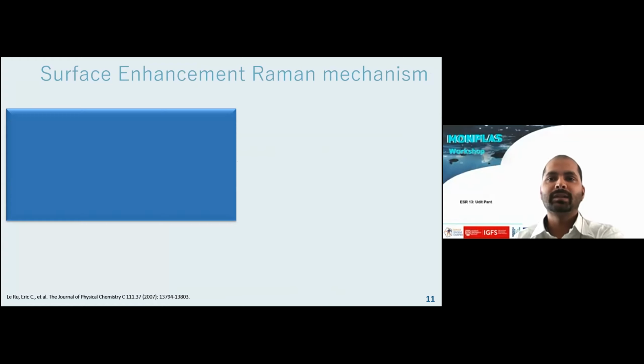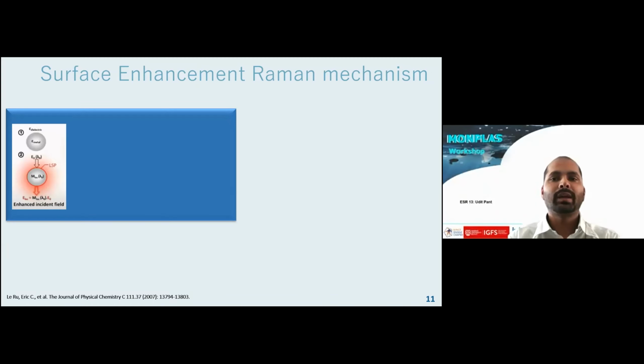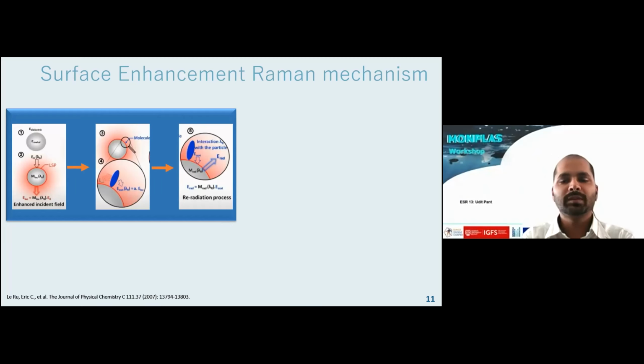There are mainly two mechanisms which are responsible for the large enhancement of weak Raman signals obtained from any analyte. First of all, Jeanmaire and Van Duyne proposed a theory based on electromagnetic effects, which was responsible for the enhancement of Raman signals. This is known as the electromagnetic theory of SERS and is based on the excitation of localized surface plasmons. Albrecht and Creighton proposed the theory based on the charge transfer effect of the adsorbed molecule on the surface of the substrate. This is known as the chemical enhancement.